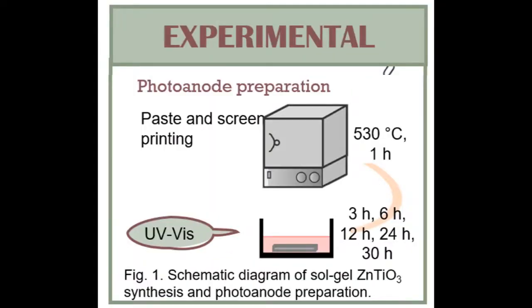To produce the photoanodes, we prepared a paste of our material using terpineol, ethanol, and ethyl cellulose. This paste was deposited on the substrates by a screen printing technique to ensure a homogeneous deposition. Thereafter, the photoanodes were thermally treated at 530 Celsius degrees for 1 hour to eliminate the organic compounds. The photoanodes were immersed in an ethanolic solution of N719 dye for 3, 6, 12, 24, and 30 hours.